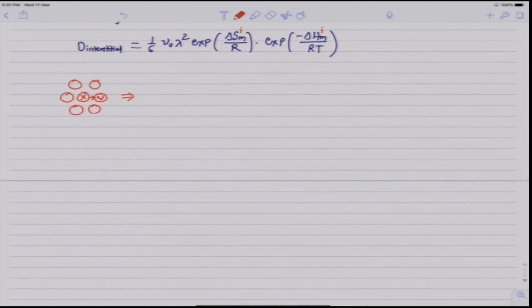So, after the jump, the vacancy is in the middle here and the atom is at X. Now, the second jump of X would no more be random, because now there exists more than random probability that the vacancy exists as a nearest neighbor of X, because the X had just exchanged with this vacancy. And what would be that probability? Of course, it will not be unity, but it will be more than random.